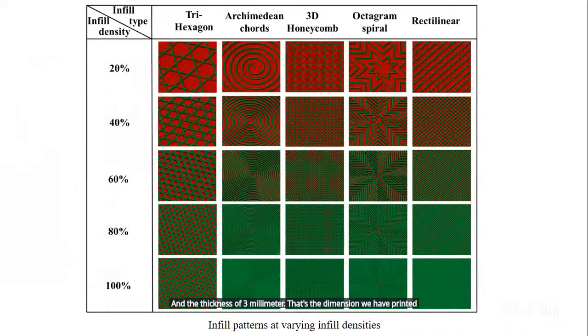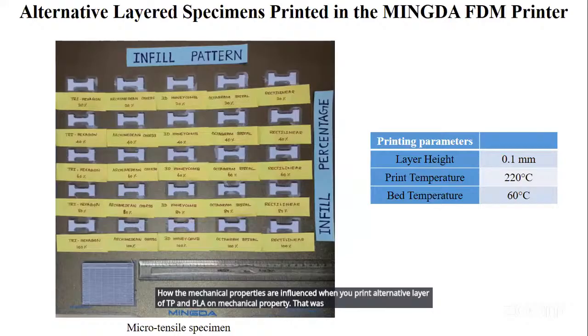We have used various process parameters like infill type: trihexagon, archimedean, 3D honeycomb, octagram, spiral, rectilinear. Then we varied the infill density: 20%, 40%, 60%, 80%, 100%. We want to know how the mechanical properties are influenced when you print alternative layers of TPU and PLA. That was the whole idea. These were the constant process parameters used to print these 27 samples, L27: layer height 0.1, print temperature 220 degrees centigrade, bed temperature 60 degrees centigrade.